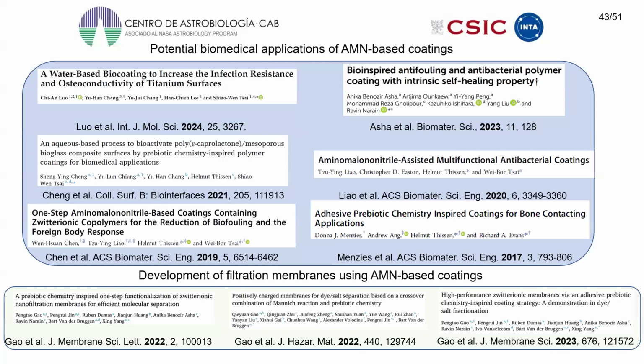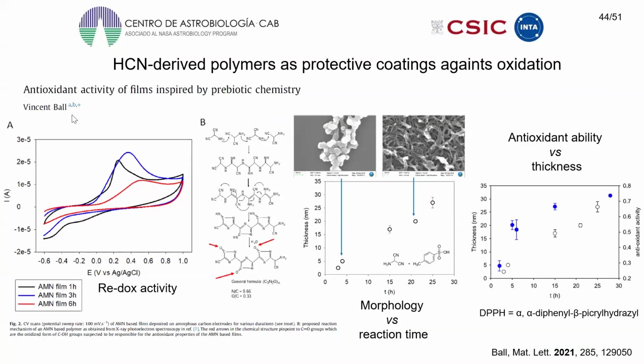Scientists worldwide, Thissen and other groups, have reported several papers about the potential application of aminomalononitrile based coatings in biomedicine due to the capacity of aminomalononitrile to produce biocompatible films. Also, the potential of this coating has been studied to develop filtration membranes. Moreover, Ball modified electrodes using aminomalononitrile solution, enhancing the redox properties. Film thickness and morphology varied with the reaction time. Using the DPPH method as a standard antioxidant assay, Ball tested the antioxidant capacity of this film inspired by prebiotic chemistry.